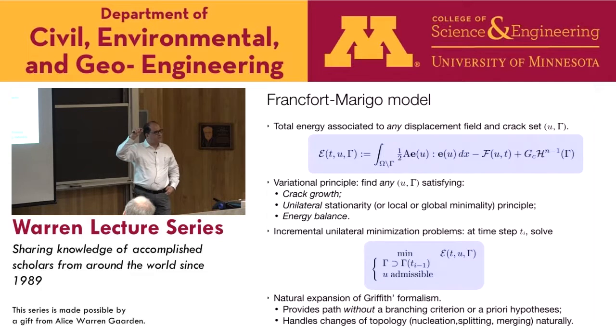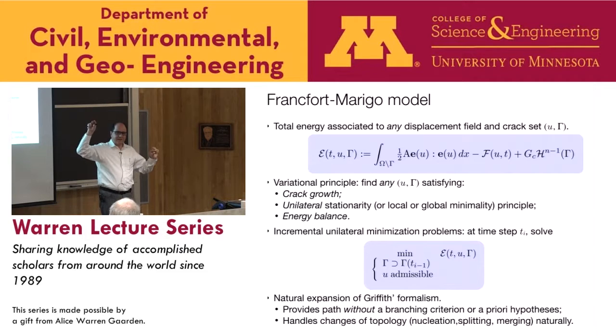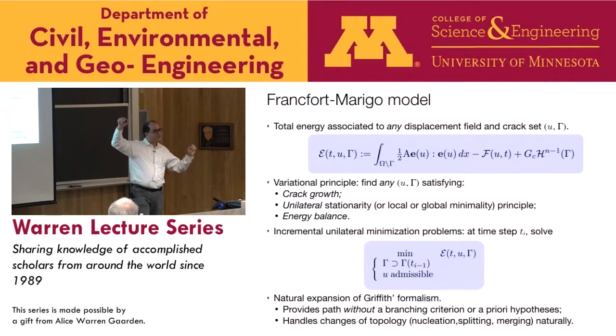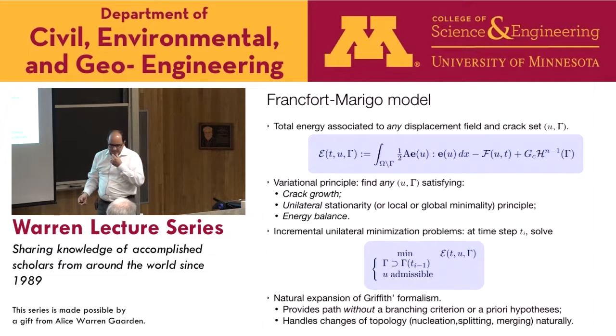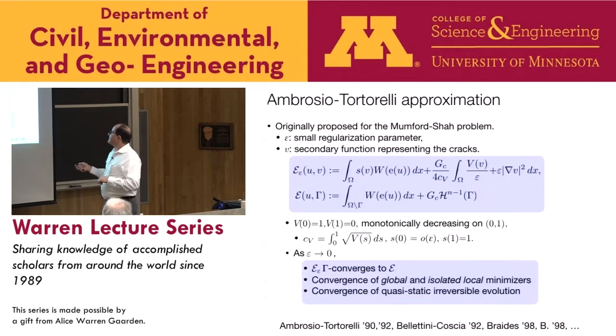What seems very silly, excuse me, but is actually quite challenging, is that you not only need to know where your crack is, but you need to know how long it is. And not all approximations of the location of a crack will also give you an approximation of the length of the crack. One way to think of this is what's called the taxicab metric. In New York, or in any city with a grid plan, if you want to go to two points that are not along the grid line, you're going to do that by following this checkerboard pattern. But the length of your path is never the same as the bird fly distance, no matter how small your grid is. So you can approximate the location of your optimal path, but you never approximate the length of your optimal path.